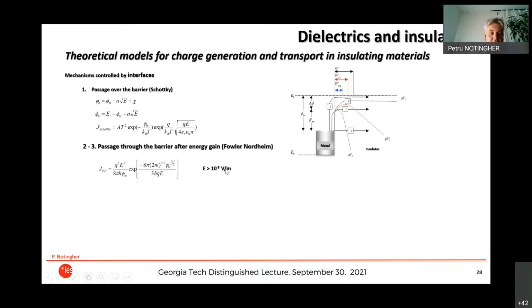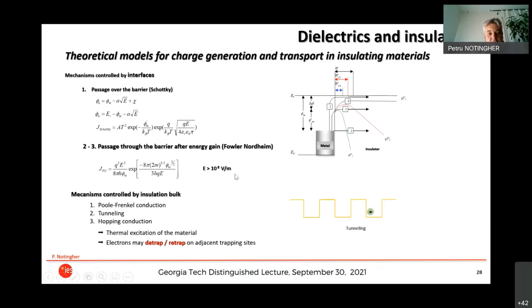If the fields are very high, above 100 kilovolt per millimeter, then you'll have tunneling. Tunneling is a quantum effect. This means that the charge will not jump over the barrier, but it will travel across the barrier. And in the bulk, you will have also what is called hopping. So that means that the charge will move from trap to trap in order to ensure conduction. So this phenomenon of trapping and detrapping of the charge is the most important in dielectrics, because there are not many free carriers. There are very few. So the conduction in the insulating materials occurs mainly by hopping, and the injection is due to the Schottky effect or Fowler-Nordheim effect for very thin layers, because you have to have very high fields.